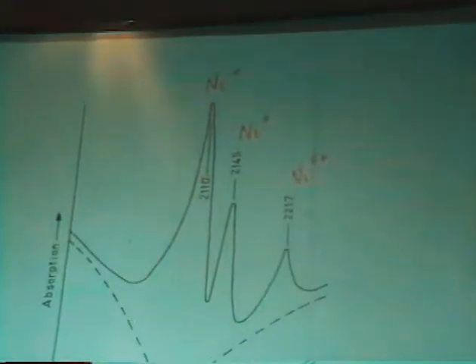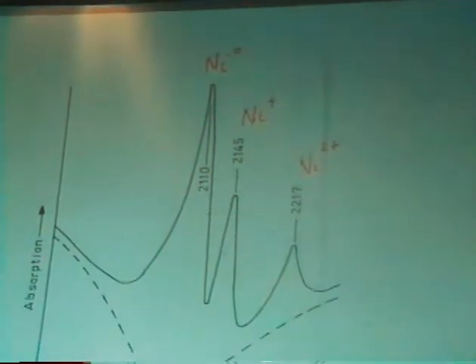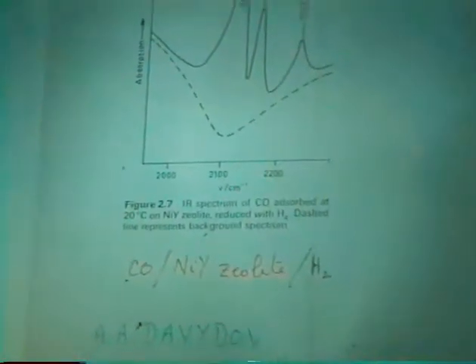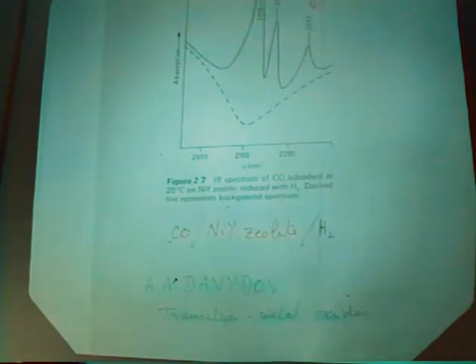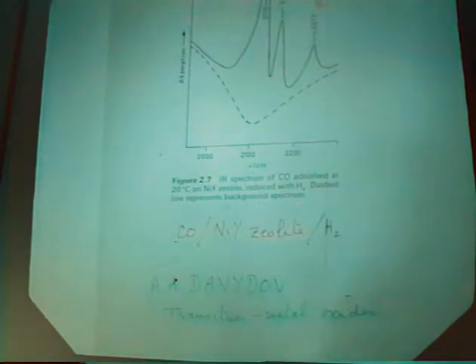CO can go on the transition metal oxides and can readily help to pick out the presence of different oxidation states. This is the work of A.A. Davydov from Novosibirsk in Russia now, and I draw your attention to a book that he's written on the spectrum on transition metal oxides. They've done a great deal of work on this in Russia, and we tend to be rather ignorant of it. And here you've got a partially reduced nickel catalyst where the CO is showing up separately, the fully reduced nickel and the different oxidation states.